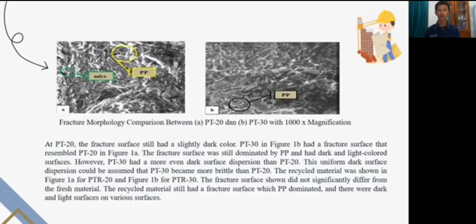The recycled material was shown in figure 1a for PTR20 and figure 1b for PTR30. The fracture surface shown did not significantly differ from the fresh material. The recycled material still had a fracture surface which PP dominates, and there were dark and light surfaces on various surfaces.